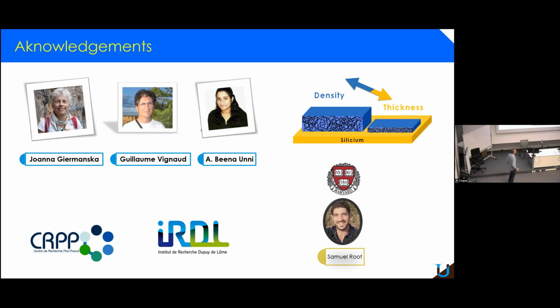I agree with that. If you average that, this cannot. And for all my feeling from simulation, what can change the density when you improve the packing? Crystallization, for example, makes you change the density up to 20%. And I think here you stay amorphous. Or maybe 30, but that's really generally the maximum. And I don't see that in an amorphous system you can have 50% or more density change.